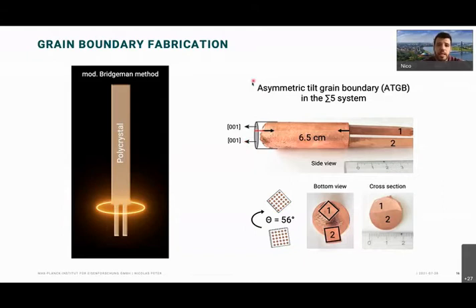What we formed is an asymmetric tilt grain boundary in the sigma 5 system, meaning that the rotation of the two grains is not symmetric, as many people observe at the moment. It's asymmetric, and we did this on purpose to be a little bit more realistic, because symmetric boundaries don't happen too often in real materials.